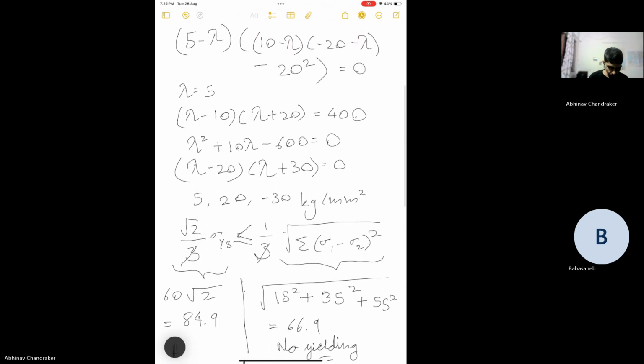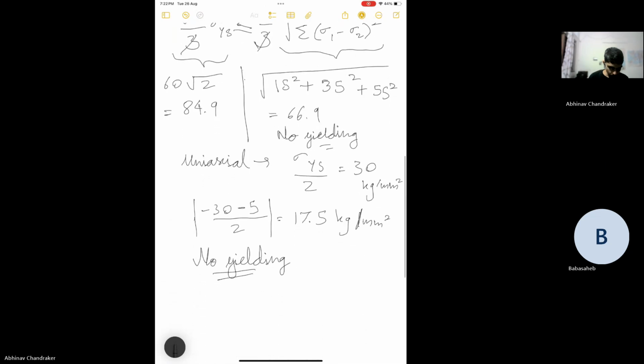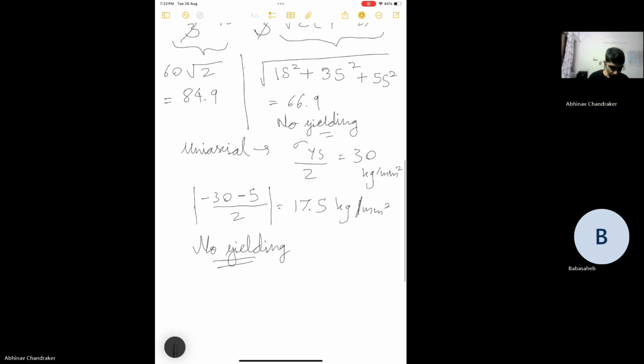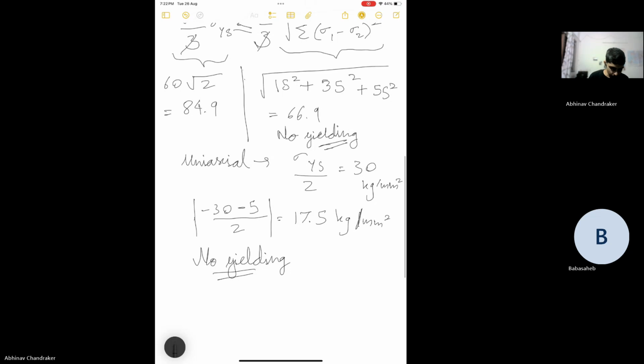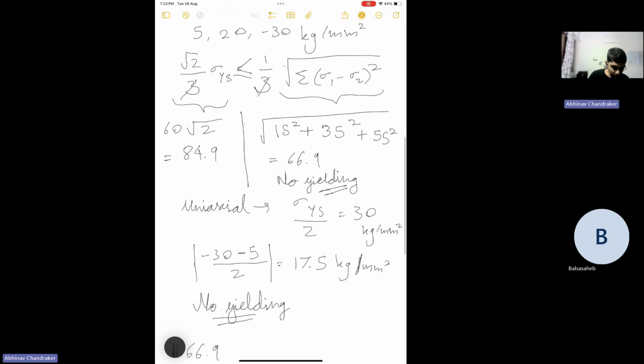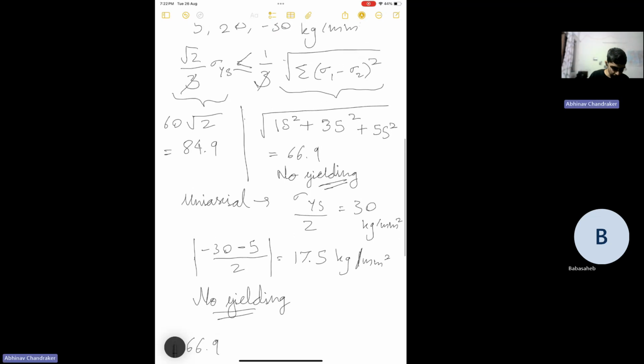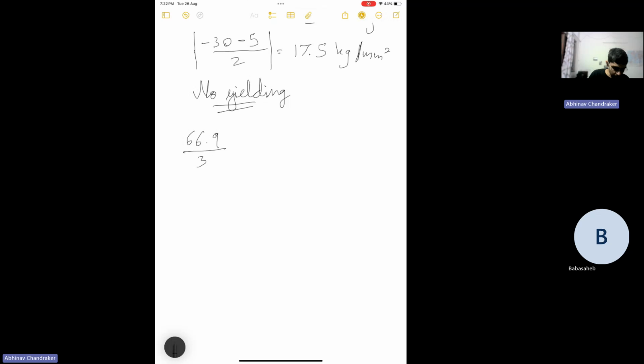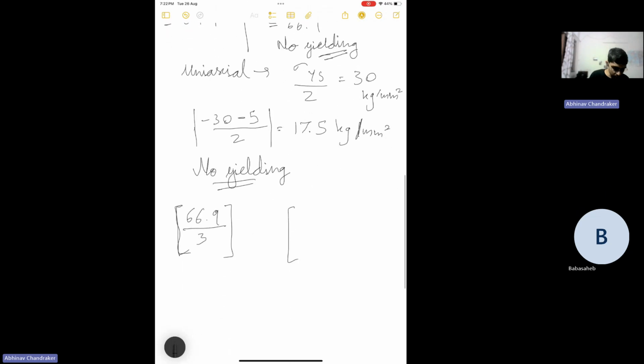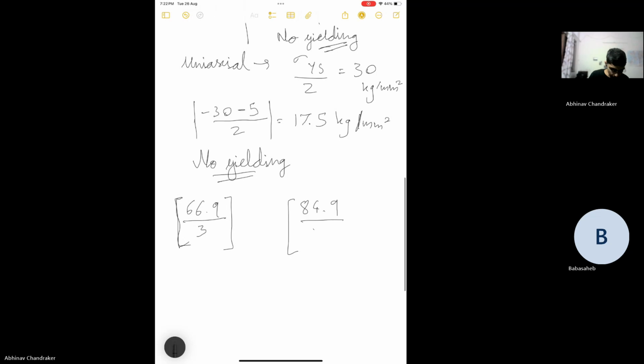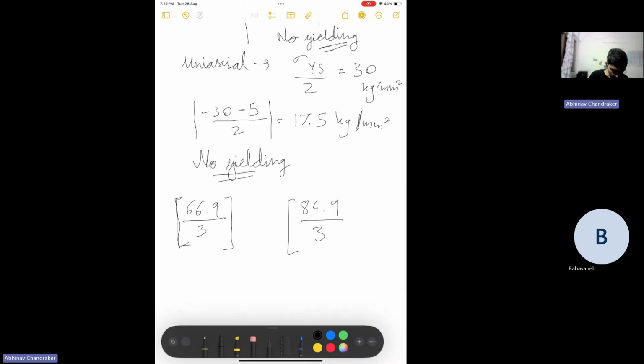So we can say that if it experienced this value of 66.9, as we can call this the composite stress value, which we calculated using this equation, or let's just use 66.9 by 3 as the shear stress value on the octahedral plane for our current stress state, and the one which will cause yielding was 84.9 by 3. Sorry, yeah, by 3.